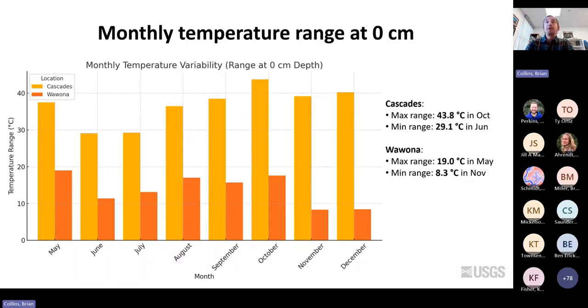When analyzing the monthly temperature range at the surface, we can see on this graph that on the south-facing Cascade side, we have a maximum range of almost 44 degrees centigrade in October. Usually the highest ranges are in October, November, and December, and we expect to have it also in February, in the spring or end of winter. While on the north-facing slope, the highest temperature range was in May, and then at the end of summer in August, September, and October.